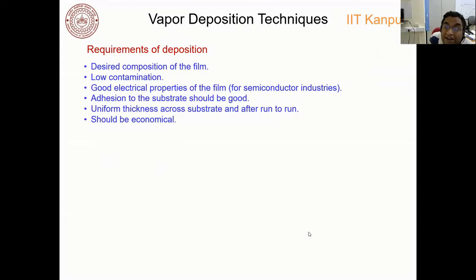And there should be low contamination, right? I will talk about that. We normally use a target material to coat the substrate, so the contamination may come from there. So we have to make sure that there is low contamination inside the thin film that is deposited on the substrate. For semiconductor industries, electrical properties are very much important. So if you are putting a dielectric material, then you should not have any electrical conductivity inside the thin film. And if you are putting electrically conducting material, then the electrical conductivity of the thin film should be preserved.